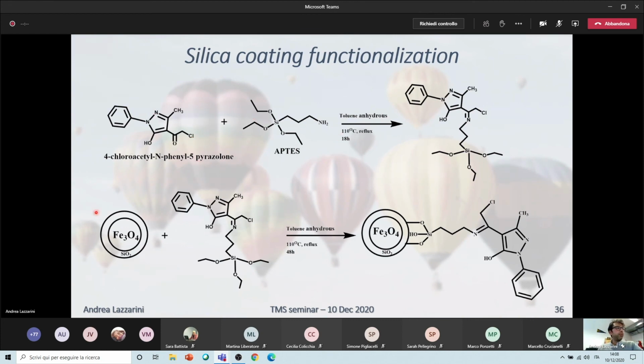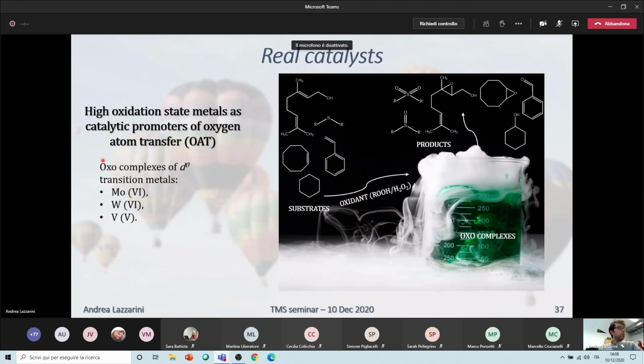And once you have produced your anchoring point, that is this point between the nitrogen and the oxygen, it can bind different metals. You can graft and anchor different moieties like molybdenum, tungsten, vanadium, and you can go through oxidation of different substrates that can be olefins, terpenes, sulfides, you name it, and you can obtain oxygenated products of these species.